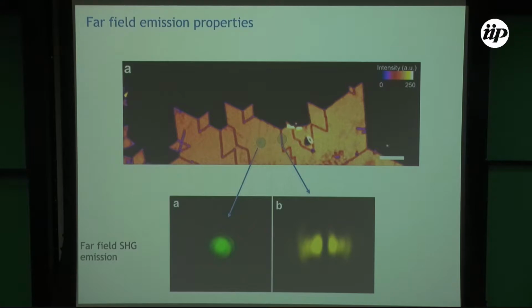But when we put the laser between two grains, with a grain boundary in the middle, we see this kind of behavior. First, you see this dark line just in the middle of the spot, and this dark line is because of destructive interference between the two grains. But you can observe that you have an emission with angles that are much larger than we would expect if there was no grain boundary here. So you can see the emission of second harmonic coming with a large angle in this case.